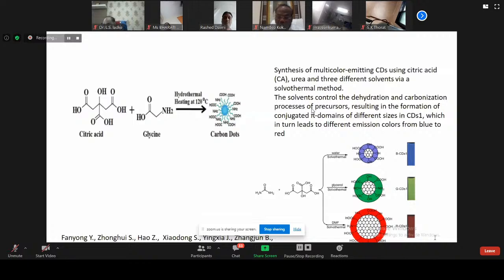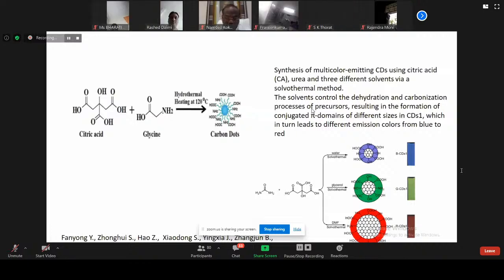So in that case, you see the nature of the carbon dot that I have and the fluorescent properties, emitting blue colors. When it is under a glycerol solvent, I'm getting a green color, and you can see the surface groups are changing or rather increasing. Under dimethyl formamide, I'm getting a reddish or pinkish color, which shows that the nature of the solvent too will affect these materials as well. So I can play around with my materials to get whatever fluorescent properties that I want.